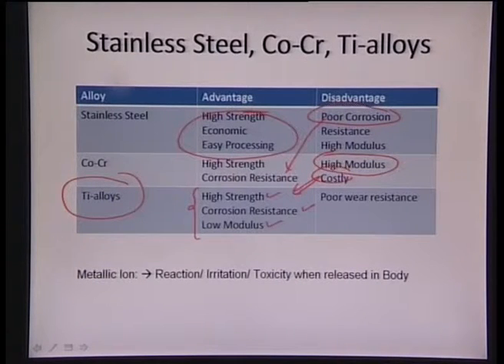But the only problem with titanium alloys is that they have very poor wear resistance. To counteract the poor wear resistance, titanium alloys generally need to be supplied with some sort of surface coating. Surface coatings take care of the wear part, so they enhance the surface wear resistance of the titanium implant. At the same time, we can also apply a coating which is much more biocompatible in nature, and which can assist bone integration onto its surface.